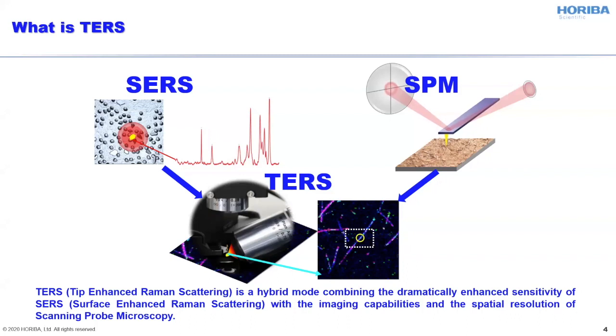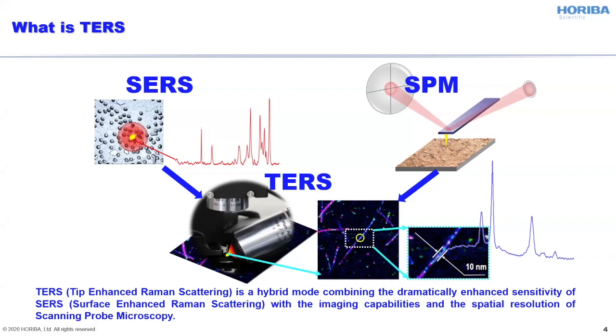So when we scan the sample under the tip under illumination, we can get a full Raman spectrum or PL spectrum, or a combined Raman and PL spectrum, in every pixel, and then we can analyze the composition of the sample based on the Raman signature or PL peak position. And as I mentioned before, the spatial resolution can become much better compared to what it is in confocal Raman imaging. There have been a number of reports in the literature where scientists demonstrated submolecular resolution in TERS imaging in ultra high vacuum conditions.